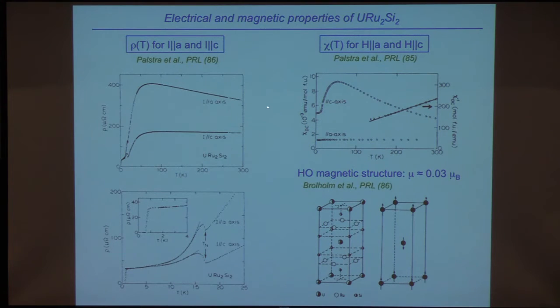And these are single crystals, so you again see the kind of behavior that I showed you, kind of like resistivity, and then it turns over and drops precipitously. But in this case, you find some kind of order that occurs at 17.5 Kelvin that looks very much like a spin or charge density wave transition. And then at lower temperatures, it becomes superconducting, as indicated here. And then if you look at the C-axis susceptibility, it has Curie-Weiss behavior at high temperatures, and then rolls over, and then has a drop due to this order, whatever it is.